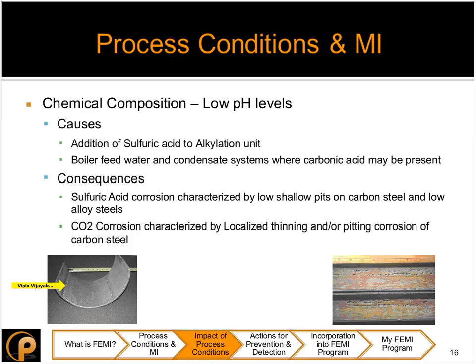Now, in boiler feed water systems and condensate systems, you might have dissolved carbon dioxide, which can turn into carbonic acid and cause CO2 corrosion, which is characterized by local thinning and pitting on carbon steels. As you can see right here, the image on the right is a pretty good picture of some pits and some thinning that happened on steels that were exposed to this kind of corrosion.